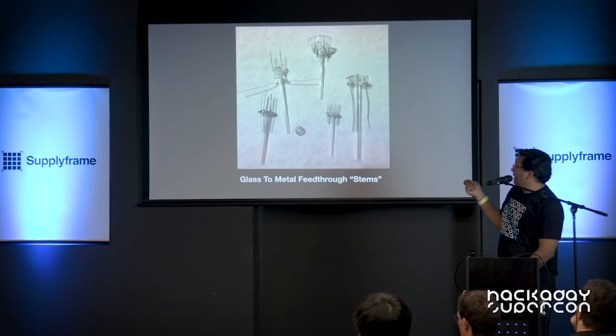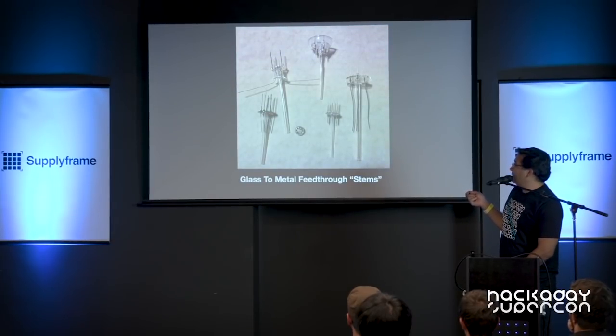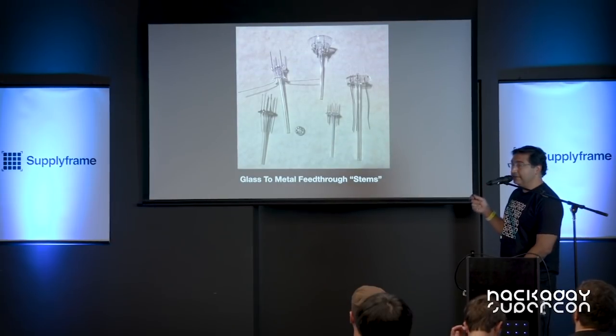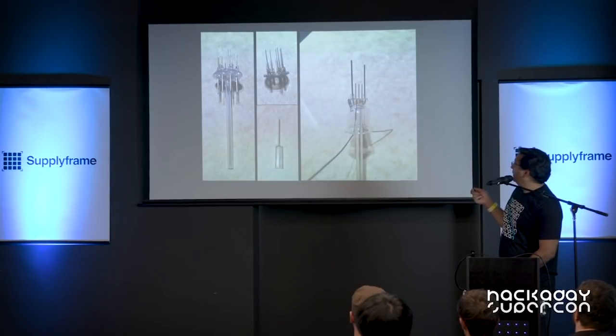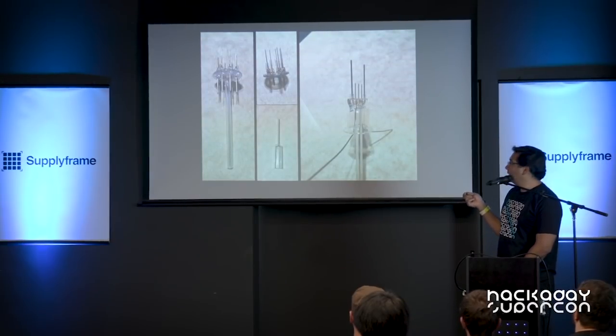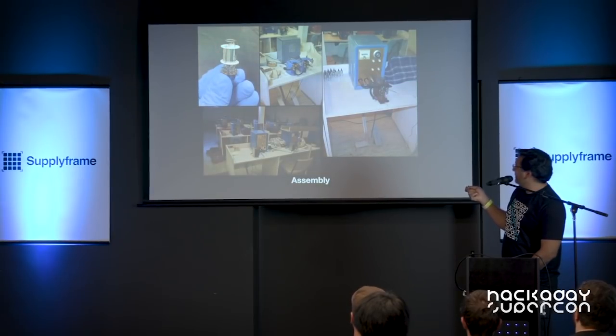These components actually comprise the metal-to-glass seal to get your current in and out of the tube. Generally speaking, they fall into two categories, wafer or flat-press devices. Flat-press devices like this, which sometimes contain the exhaust tubulation and sometimes do not, just depending on the design of the part. What will happen is you'll build up the internal tube components by spot welding on top of it, making what used to be referred to as a mount. That then, in turn, might look something like that.